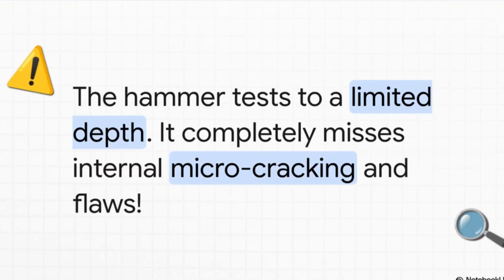Okay, here is the fatal flaw of the rebound hammer if you try to use it entirely on its own. It is incredibly short-sighted. The rebound index is only indicative of compressive strength to a very limited depth from the surface. Think about it. If the concrete member looks perfectly hard on the outside, but has deep internal microcracking, hidden voids, or major structural inconsistencies across its cross-section, the rebound hammer is still going to bounce back beautifully and report a high strength. It remains completely blind to the actual internal reality of the structure.